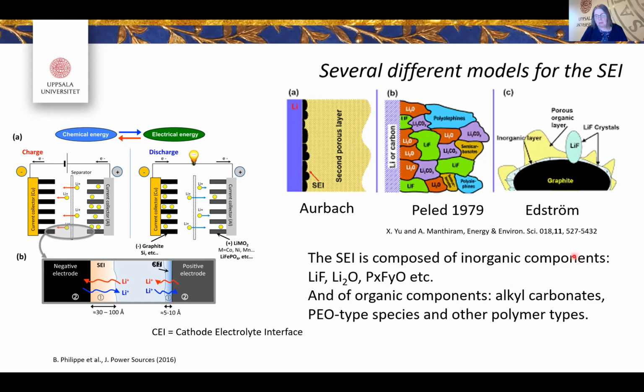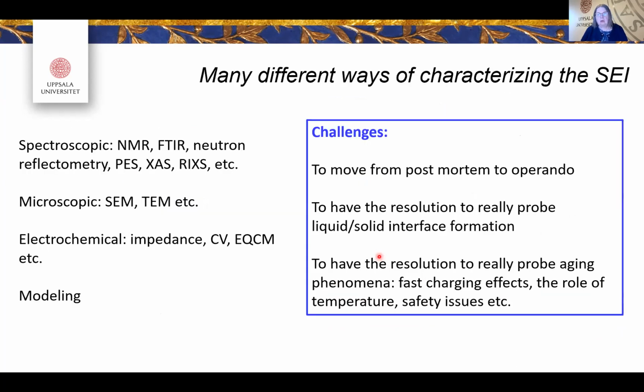And in practice, the SEI is composed of inorganic compounds, lithium fluoride, very important, lithium oxide, less of that, some salt reduction products, and organic components like alkyl carbonates, PEO type species, polymer types, a whole range of suggested compounds. So I will focus on photoelectron spectroscopy, but there are many other kinds of methods you can use. I would say that in particular NMR is now coming as a very interesting complement. But of course, you can learn a lot about these interfaces just by looking at the electrochemical signals as such, and you need always to complement it with SEM and TEM studies.